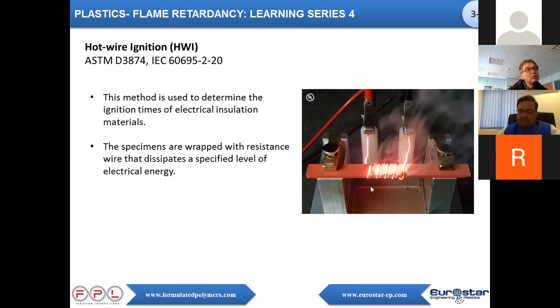Basically, you wrap a wire onto a UL bar, like KK described. You apply a current, and then you measure the time to collapse. The collapse is measured by flaming, or if the material survives well, sometimes you have a material which is melting and vanishing from the wire. The time has to be stopped when there is no more material to be burned.